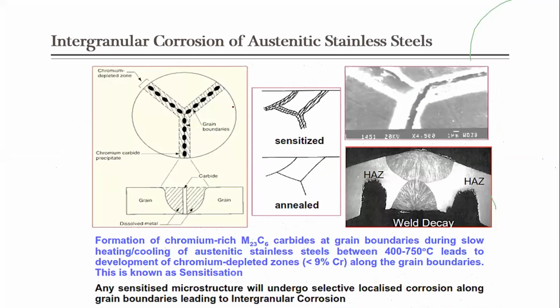And coming to the intergranular corrosion, it mainly occurs because of the sensitization. Formation of this intergranular corrosion is enhanced mainly because of the sensitization process. The formation of chromium-rich carbides at the grain boundaries during slow heating or cooling of austenitic stainless steels between 400 to 750 degrees centigrade leads to the development of a chromium depleted zone. That is nothing but a sensitized layer along the grain boundaries, which is known as sensitization.